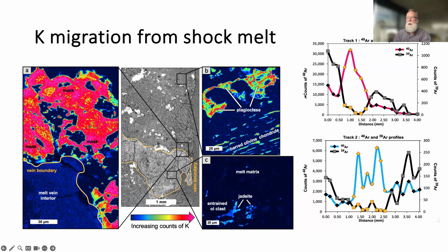And we see that here in the Argon-40 versus Argon-39. So the Argon-40 is high in the melt vein. The Argon-39, the proxy for potassium, goes almost to zero in the melt vein. That's for the red track. For the blue track, similar, the Argon-39 goes way down. This is telling us that the potassium in the melt vein migrated out, but the argon did not. Okay, so clearly the behavior of potassium and argon at high pressure are quite different than what one might assume.